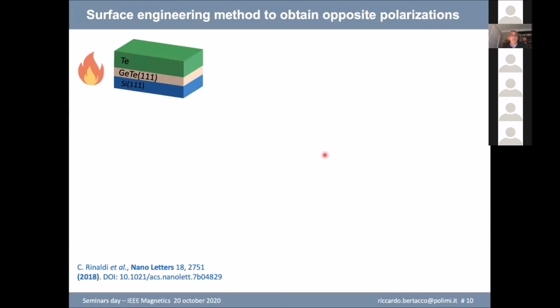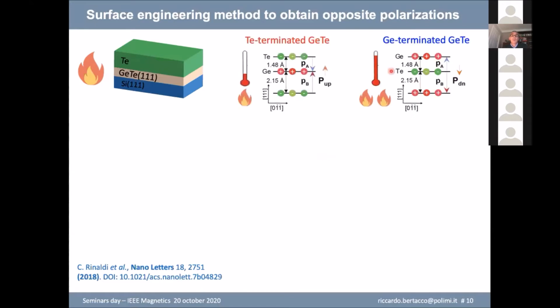So we developed this method, which is a surface engineering method in which we obtain different polarization just by creating different termination of the film. And the idea is this one: you can have a germanium terminated or a tellurium terminated germanium telluride film. And in the two cases, due to the different termination, you will have a polarization pointing upwards for tellurium termination and downwards for germanium termination. And the way you achieve this different termination is something which concerns the sample preparation. We have a tellurium capped film. So with different decapping temperature, we can achieve different termination.